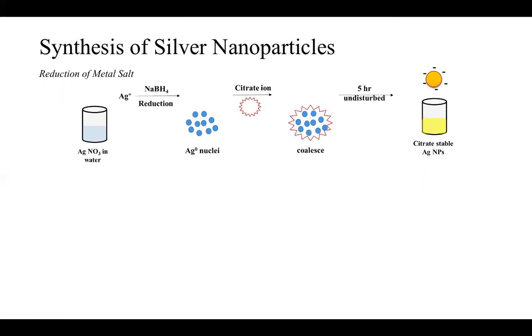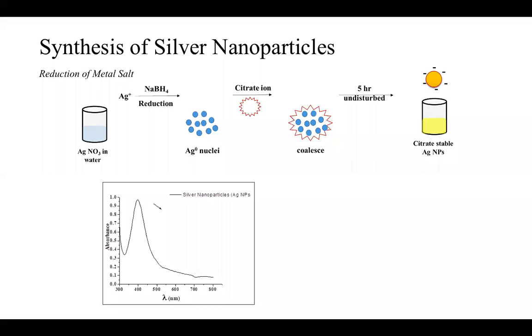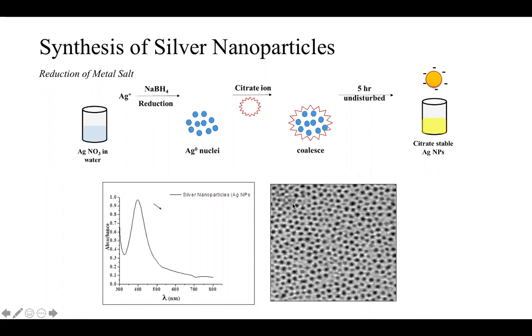One of the cool things about silver as well, unlike silver ions, silver nanoparticles have surface plasmon resonance. So that allows us to have a peek to kind of tell the size of our nanoparticles that were produced. So we were able to use a UV-vis to identify and indicate the stability and the size and uniformity of these nanoparticles. And based on this peak, we could tell that it's right around 395 nanometers, that indicates, based on past studies, that it's stable, and we've produced about 4 nanometer nanoparticles.